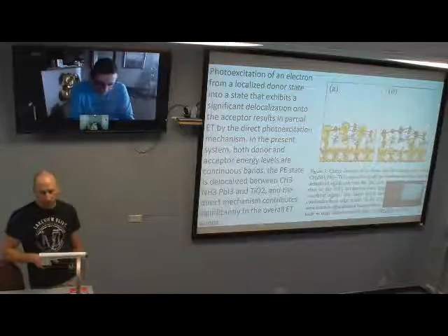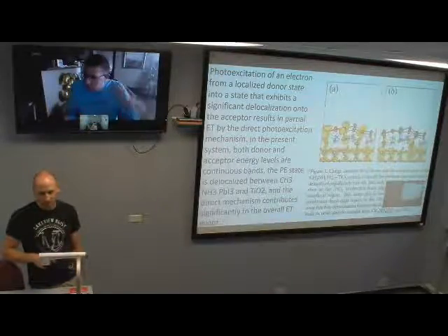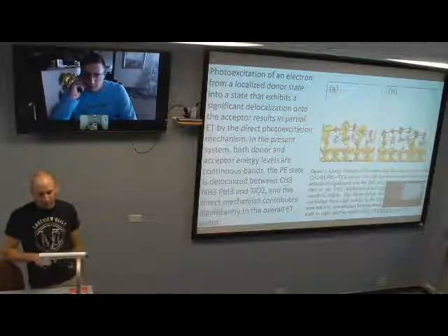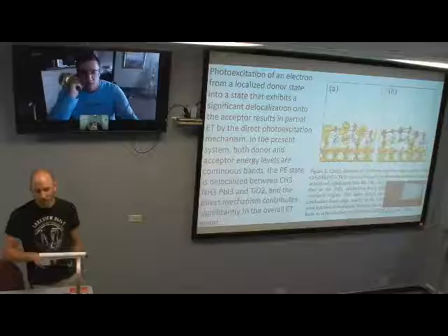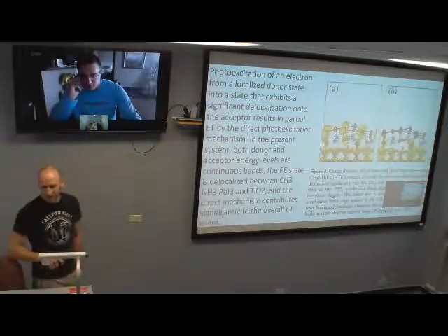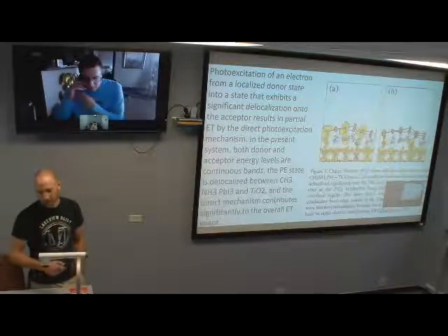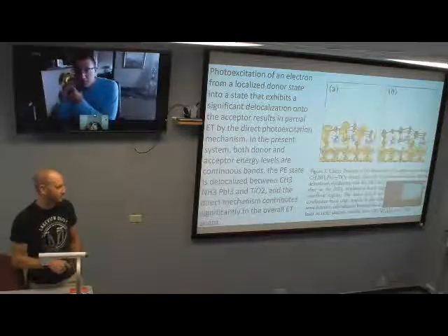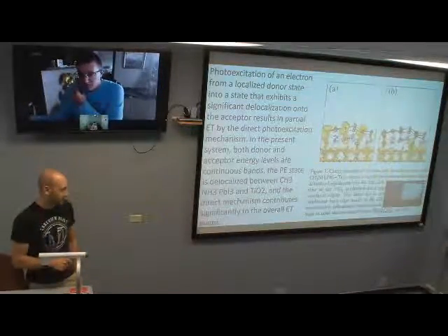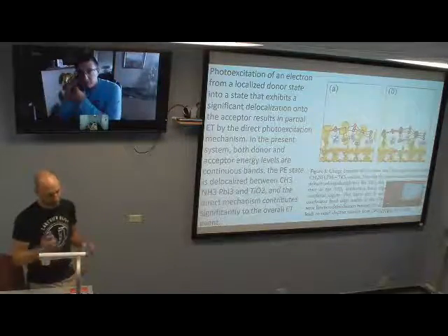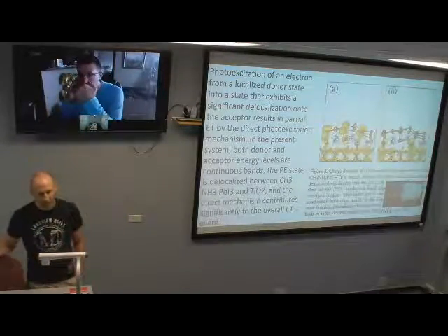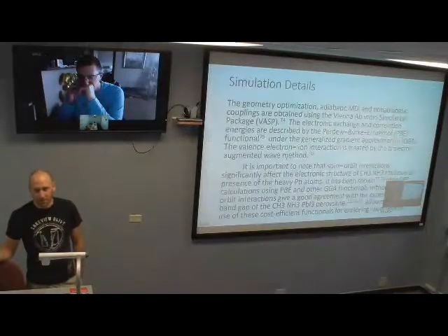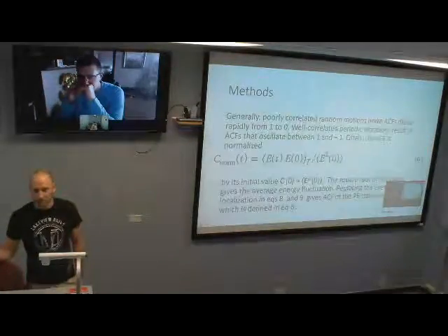Right. And in their case, they excite really hybridized states, it's both titanium and this one. Relatively, the acceptor state has much more charge density on titanium dioxide than on perovskite. It ends up more on the titanium dioxide than it was originally, but it kind of was on both to begin with, so you're not really transferring the charge. But why does it already start with this hybridization? They probably have some discussion of that.